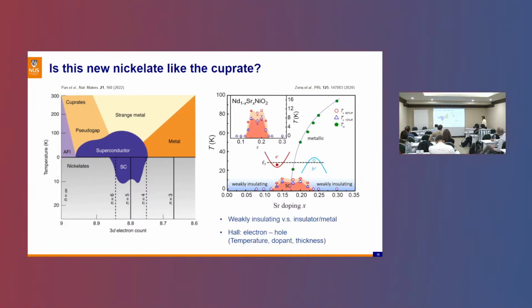And then, of course, this is the similarity, but you also notice there are differences. For example, in the case of the cuprate, we have an antiferromagnetic parent compound, while in the overdoped regime you have a metallic state. While as you can see from the first diagram of the nickelate, in the case of Nd, both the underdoped parent compound as well as the overdoped show this weakly insulating behavior. So it's basically metallic with weak localization at low temperature.